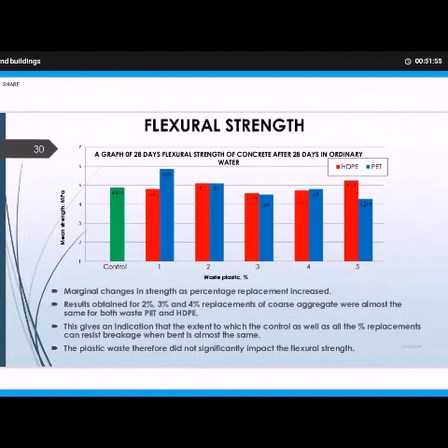But I must say that flexural strength is about 10 to 20% of the compressive strength. So even if you are looking at the highest side, that is 20%, you realize that 20% of our compressive strength, which was 20, is around 4. So it means that the minimum strength we are looking for the flexural strength should be 4 megapascal. But if you look through, we realize that all the strength we are getting are beyond 4, 4.5, 4.7, 4.8, and all that. So it means that it is very, very good in terms of flexural strength, even though we have added the waste plastic. It is still good when it comes to flexural strength.